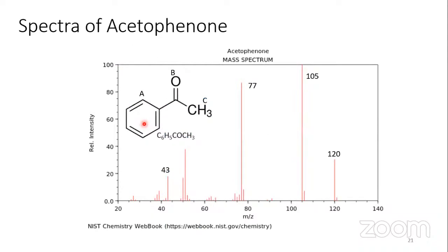I have taken acetophenone, which has a molecular weight of 120. So you can see ABC plus. I have considered this acetophenone in 3 parts. The phenyl group is A, the C double bond O group is B, and the CH3 methyl group is C. And you can see 120 is nothing but ABC. Now, what happens when this is the molecular ion? It fragments, so the methyl group is lost, and you get AB plus. If you calculate the molecular weight of this, it is 105. So you know that from 120 to 105 there is a loss of 15, and 15 could be methyl.